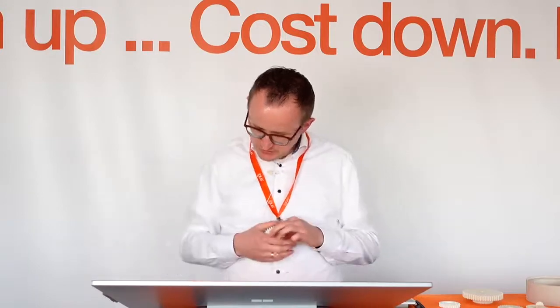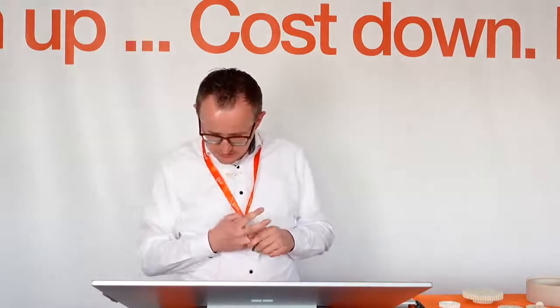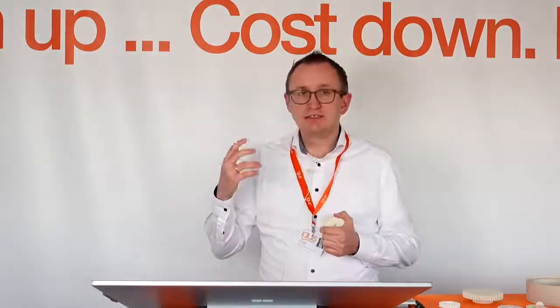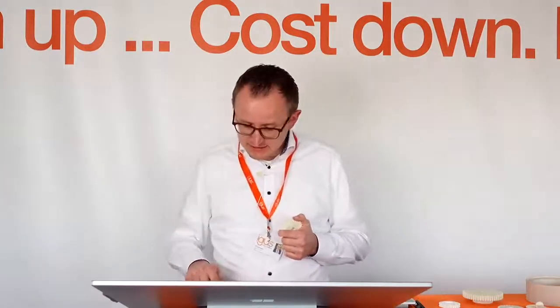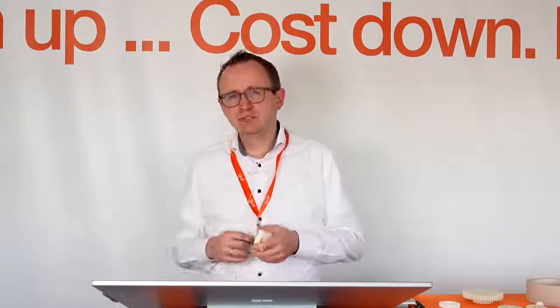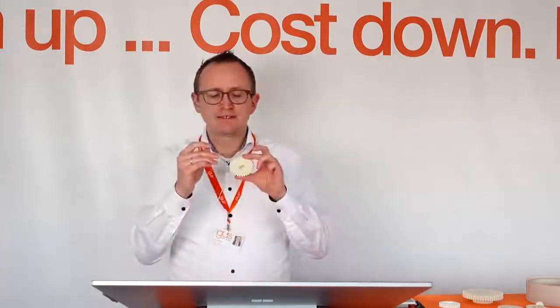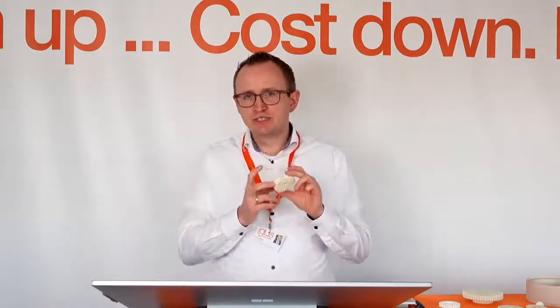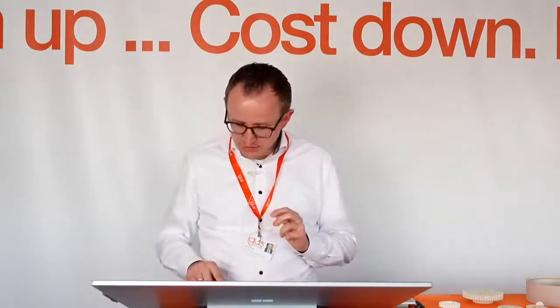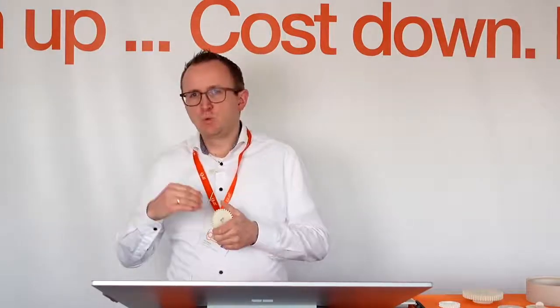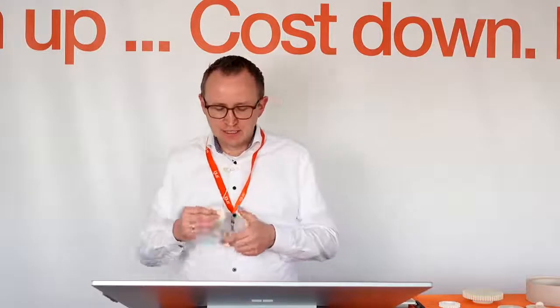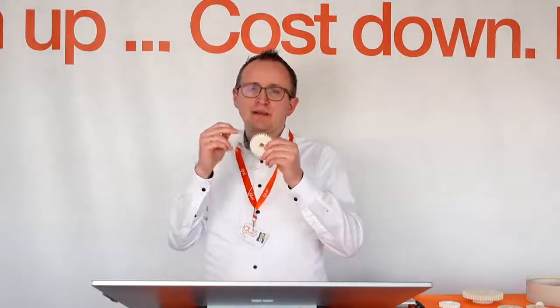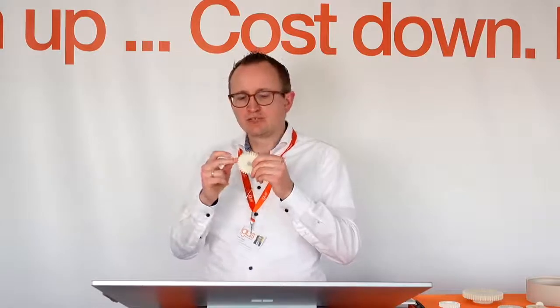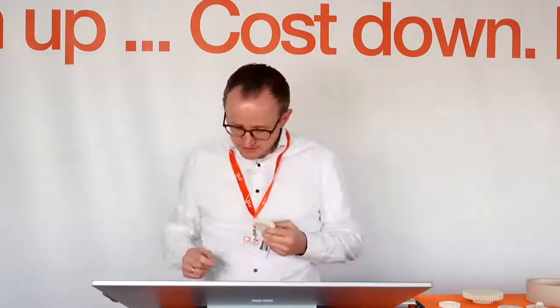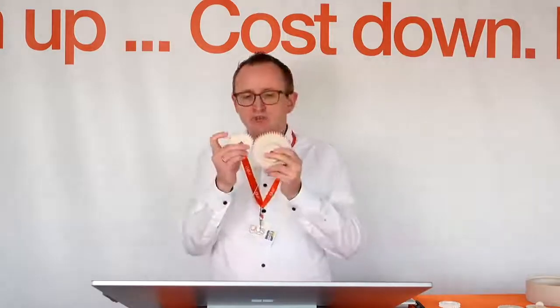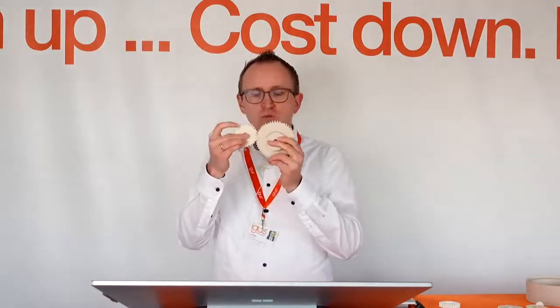What's the wear considered for the estimated service life shown in the result? Very good question. Normally with gears, wear is not such a big issue. It's more an issue of when the teeth break. You usually don't have so much wear compared to a bearing, where wear is the main issue for lifetime. With a gear, it's really the point at which the gear breaks. So the lifetime calculation calculates when the gear breaks, because if a gear works well, you don't have any sliding. It's more like rolling.